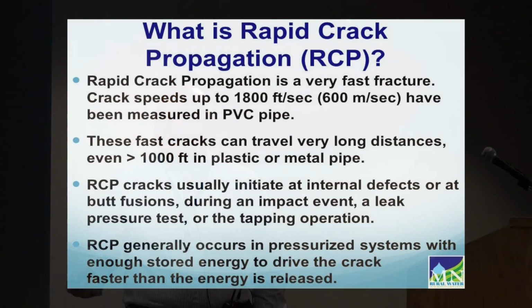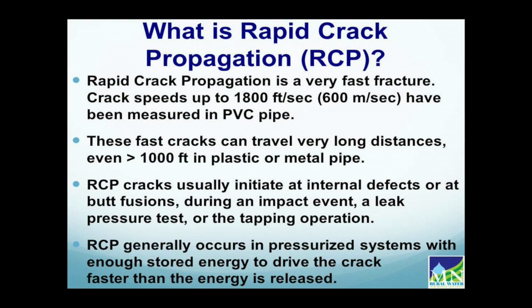That's pretty fast. So when we're talking about these long-running cracks, 1,000 feet, 1,500 feet long, they actually travel that distance in less than 1 second. So it's a very, very fast fracture. It's referred to as a catastrophic failure of the pipeline, typically related with what's sometimes called an explosion. These cracks can travel very long distances, as you'll see in some of the examples I'll show, over 1,000 feet.